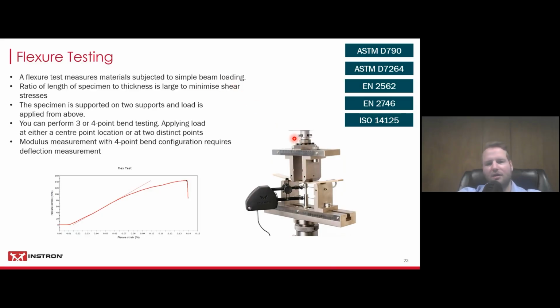You can run this in either 3 or 4 point application. So you have 2 supports on the bottom, then either 1 loading nose coming down, or in this case, like you can see here, 2 loading noses come down, and you can determine the modulus in the 4-point bend configuration, which does require, again, a measurement of the deflection right down here under the specimen.